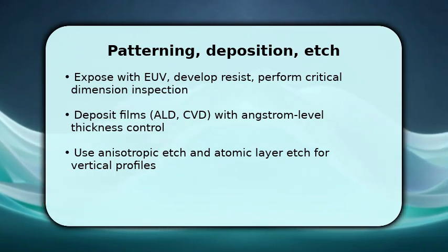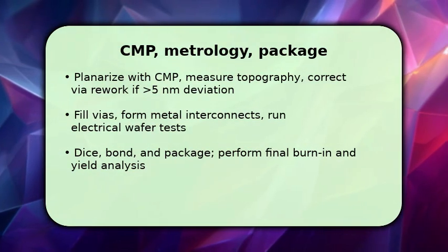You finish by planarizing layers with CMP and using metrology to verify topography. If deviations exceed a few nanometers, correct with targeted rework because uneven surfaces break lithography at 5 nm.